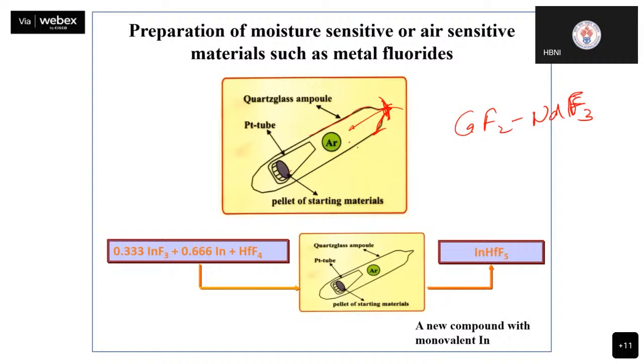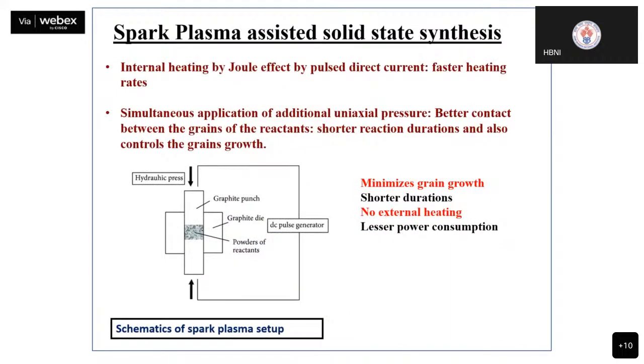Now it has vacuum inside and it has my platinum ampule, which is containing my reactant pellet. And this total quartz tube went into the furnace. Now I did not have to maintain my furnace under any special atmosphere because the atmosphere in this tube is now vacuum. Then we heated it at 900 and we got metal fluorides. So this is how we plan our synthesis.